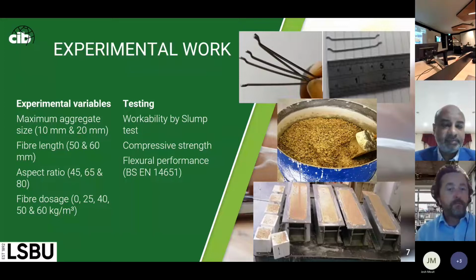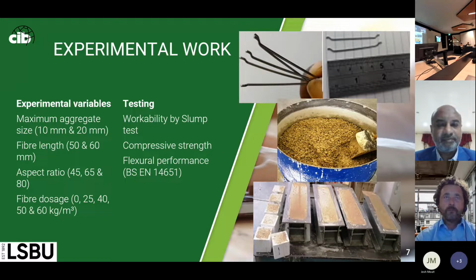So this is the experimental work. The variables: maximum aggregate size, using 10 mm and 20 mm. The fiber length, two of them, 50 mm and 60 mm. The aspect ratio, that is the ratio of length to diameter, three of them: 45, 65, and 80. Then we have the fiber dosage in the concrete: concrete without fiber at all, then 25, 40, 50, and 60 kilograms per cubic meter.